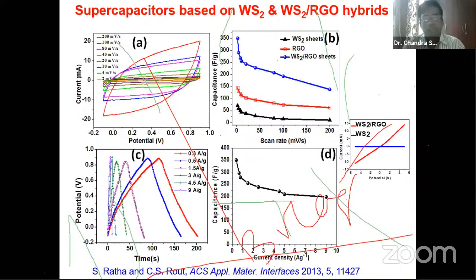These are the characteristics and data of the supercapacitor performance. We use cyclic voltammetry and charge-discharge curves, and then calculate how much energy is stored in these devices, and see whether this material is good for energy application or not. This is one example, tungsten disulfide, which is a layered material. We tried tungsten disulfide with graphene-based material. We published it long back in 2013, one of the first reports in the literature.